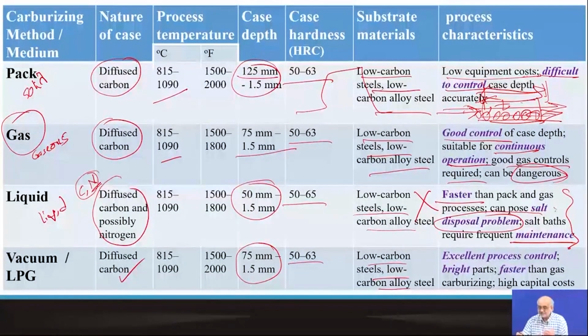In case of vacuum carburizing process, we have an excellent process control. We get bright parts because, as I told you, there is very little gas or oxygen presence in the chamber, which means I have a very good bright surface, no oxidation, no tarnishing, and it is also even faster than gas carburizing. But on the negative side, the capital cost is higher because you have to maintain the furnace, maintain the chamber at a certain level of vacuum before you backfill.